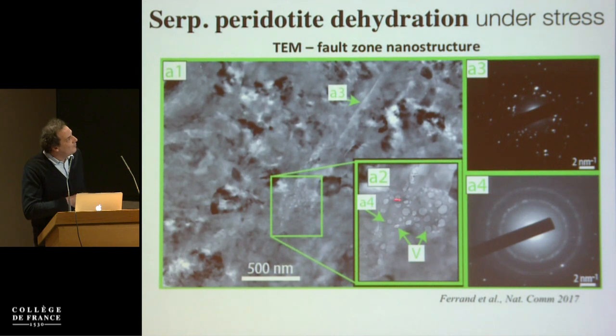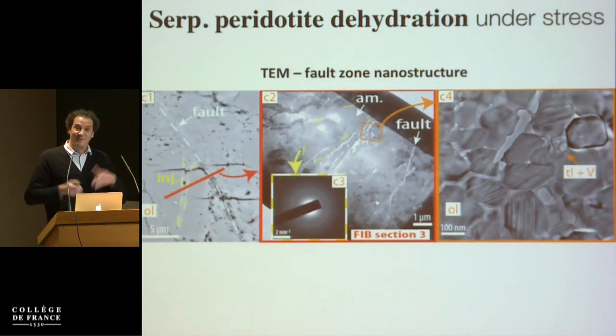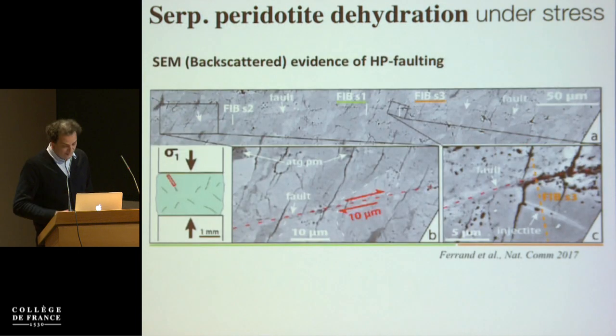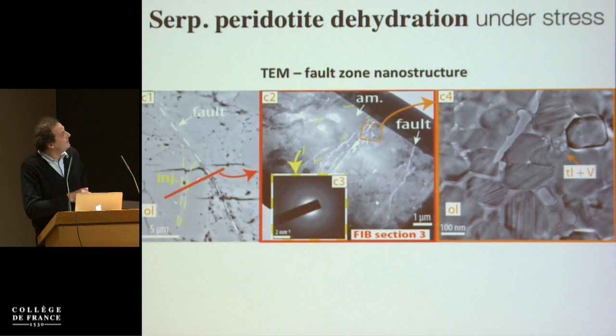And if you look in the fault, you see all these bubbles here, which are the dehydration products. So basically, in the fault, you see the remnants of the serpentine dehydration. And in fact, if you do a diffraction close to the fault, what you see here in A4 is that you have amorphous material, but you also have some nanocrystalline material, just like Giulio has shown in the calcite. But now we're talking about something that happened over a 10 micron slip only, but at very high pressure. If you look now at the second FIB section, it's cross-cutting this thing that we call an injectite. And in fact, everything here is amorphous. So we interpret this as a molten rock.